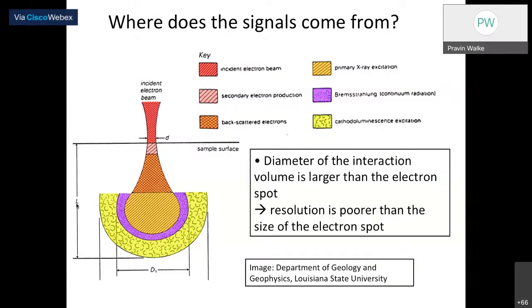So where do the signals come from? You carefully see the figure over here, right? In this left figure, different color codes have been used for the different interaction parts. For example, here you have the incident beam. The incident beam interacts with the sample here, right? The incident electron beam is given by this sort of dark pink color probably. This D is sort of resolution, right? The diameter of the interaction volume should definitely be larger than the electron spot, because the electron spot defines your resolution, right? So it means your resolution is a little bit poorer than the size of your electron spot, right? It should not be smaller than the electron spot, as I said just before.